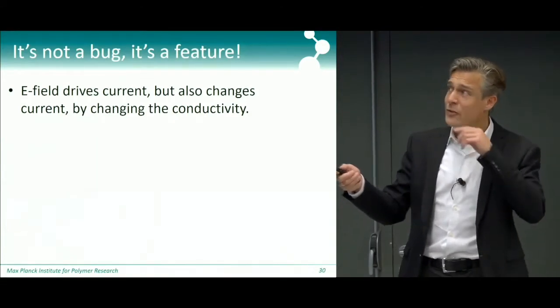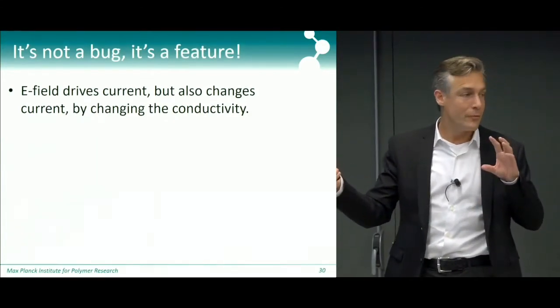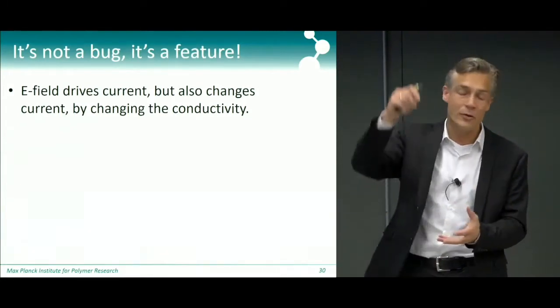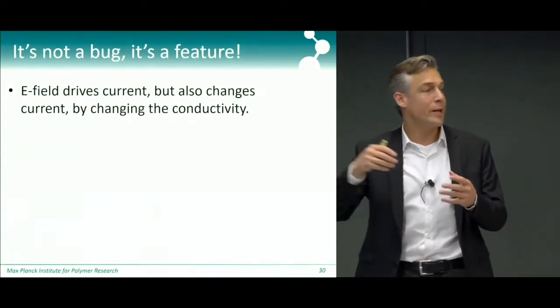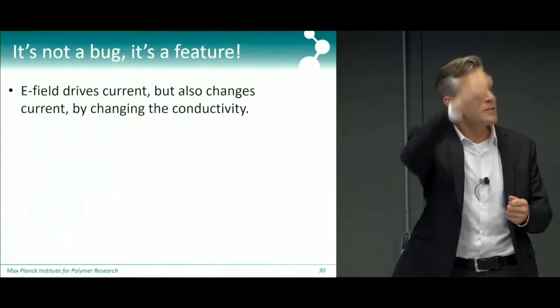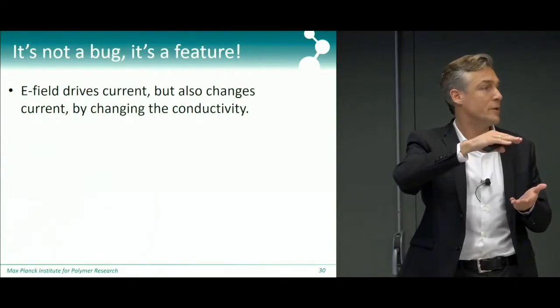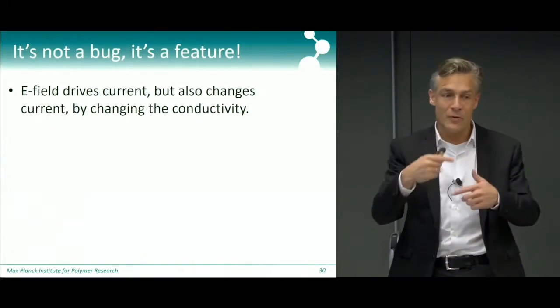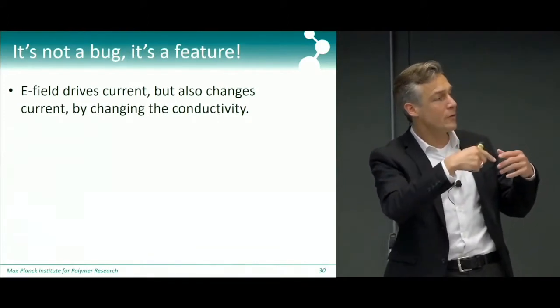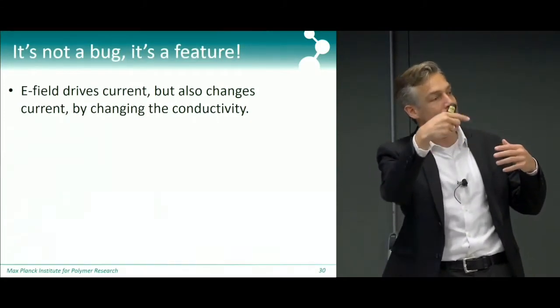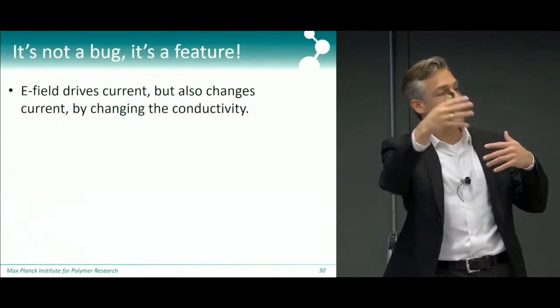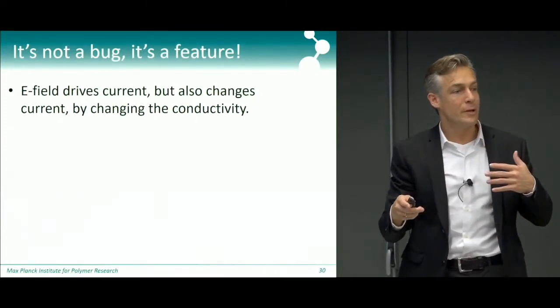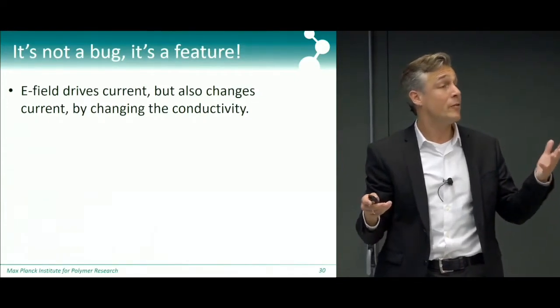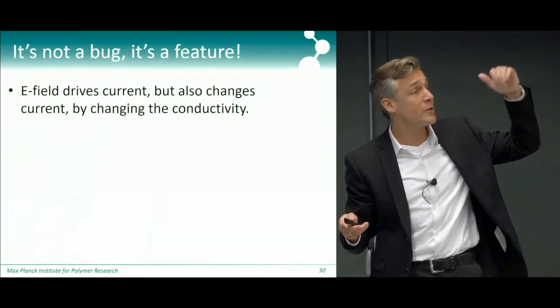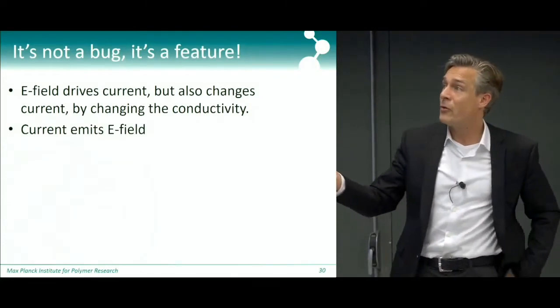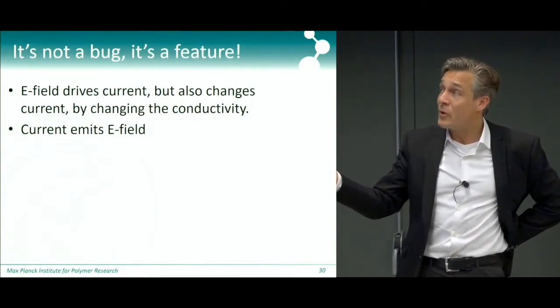And so I told you that what we do when we apply this electric field is we drive a current, but I've now also shown you that already at modest field strength, this current heats up the carriers, which reduces the conductivity. And so you get some sort of interplay between the external fields, the electrons that are heated and can cool again, and the current that is driven by that field. And it's, of course, a very nonlinear effect, because the higher the field, the more this current starts to saturate. And so the E field drives the current, but also changes the current.